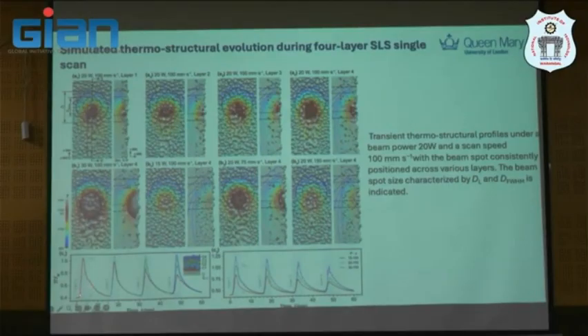So you will see that this is a thermal cycle for each deposition here. And then I think it's probably difficult to see, but you will see that the thermal cycle is not that severe compared with the real LPBF with melting, but it basically captures the trend of LPBF somehow. And this is the temperature normalized by the melting temperature.